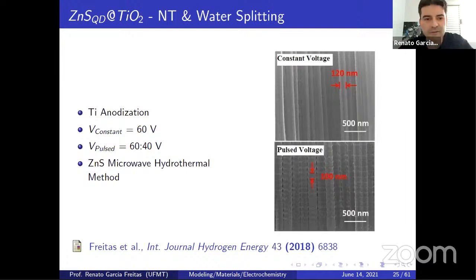defects of this one. So in this paper, we apply titanium anodization at a constant voltage of 60 volts and a pulsed one, 60 and 40: 60 volts, 40 volts, 60 volts, 40 volts. So we obtain like this one, what the guys used to call bamboo titanium oxide nanotubes, where each segment can be considered as a defect, isn't it? So if you have an electron conduction, in this part, we have a segment of defect. And we deposit inside zinc sulfide using the microwave hydrothermal method.